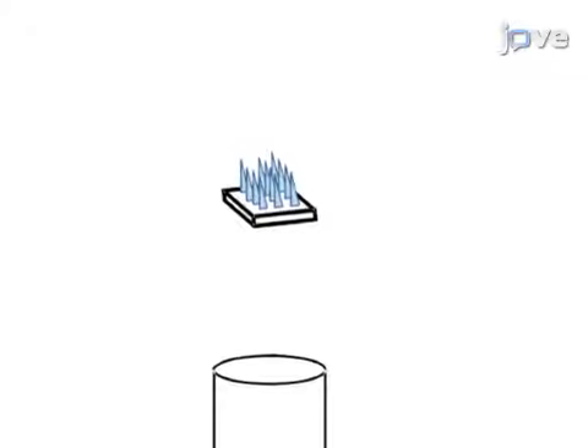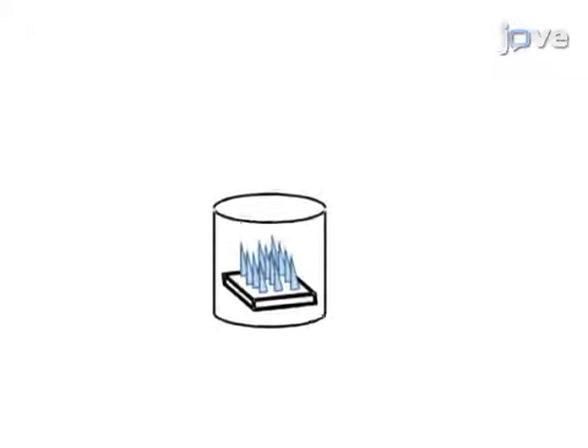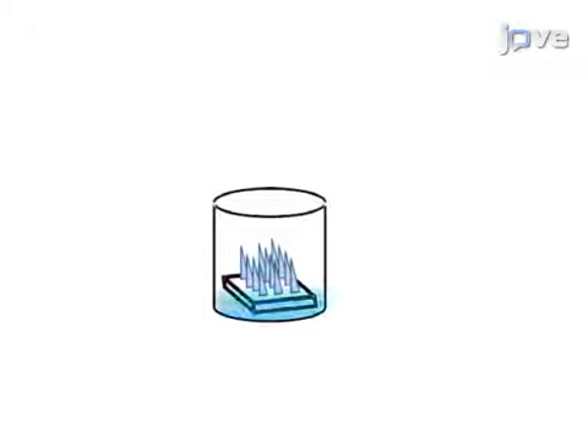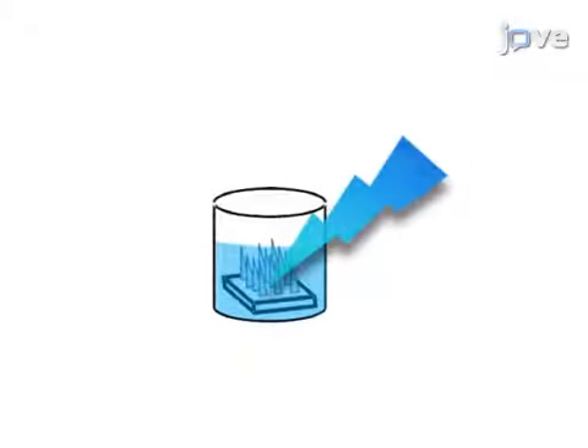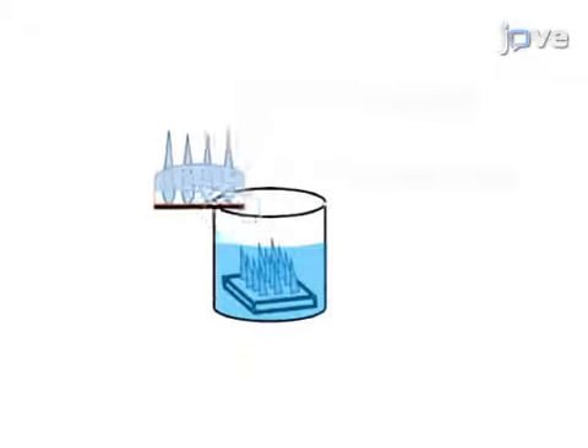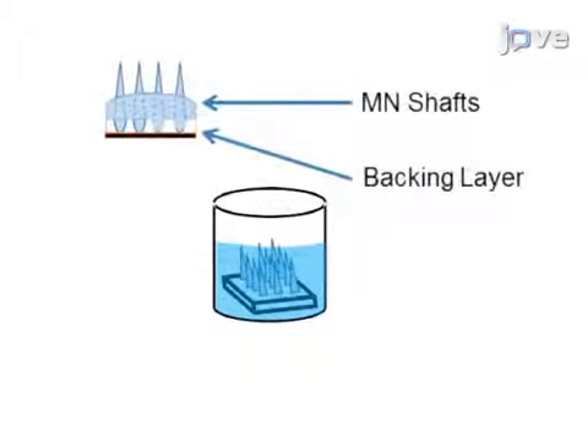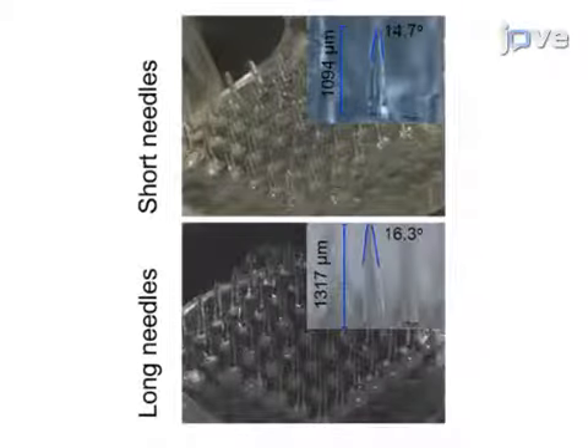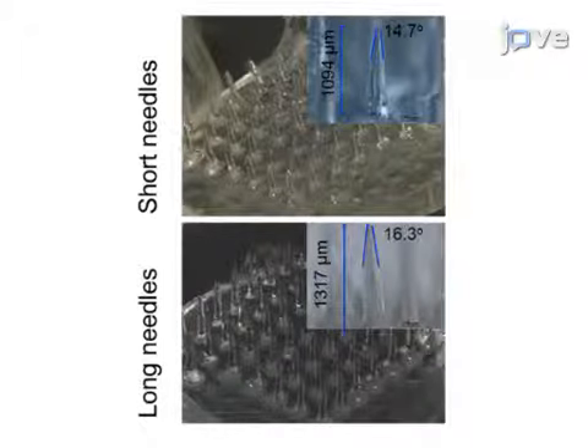This is accomplished by placing the microneedles, pointy side up, into a plate, then adding a pre-polymer solution and polymerizing the solution with UV light. Ultimately, the characteristic properties of the microneedles, including length, diameter, and the apex angle, can be observed using a stereo microscope.